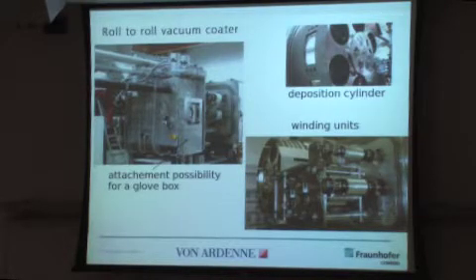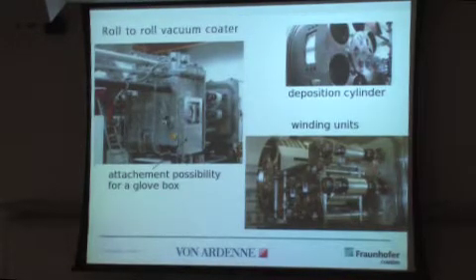And the way it works is quite simple. You have a big vacuum tank, and in that vacuum tank at the door you have here the plastic foil. This is 30 centimeter foil, and you unwind it and pull it around a big cylinder which is rotating. And around this cylinder, not really visible, they are up here, you have the organic sources. These are linear sources, and they are put next to each other. And what you do is you evaporate all these 10 or 12 layers in one run. While you pull around once, you evaporate all the layers. So it's very efficient to coat, and you need only one run around it. The desired speed would be that you reach several meters per minute, and then you can produce these cells very efficiently. And there's one very economically important point.